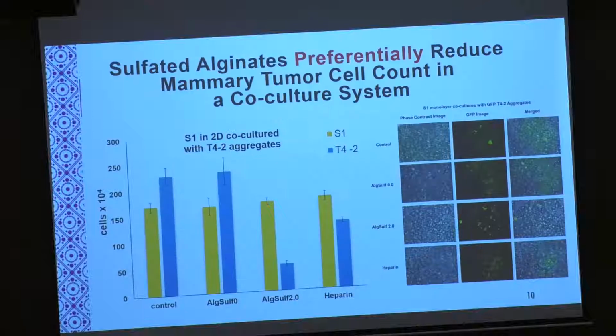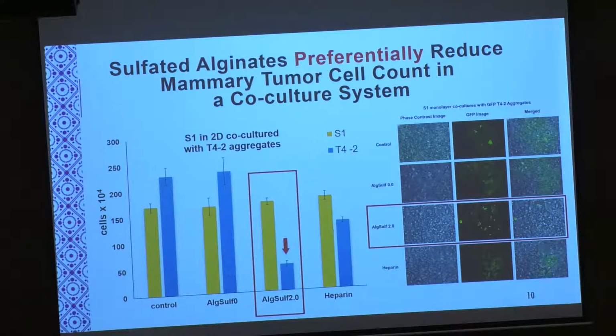And finally, we're saying all the time that these alginates are preferentially reducing the proliferation of the cancer cells and not the normal cells. So a co-culture system was a perfect approach for us. We cultured S1 cells, and we added on them T4 cells that are GFP labeled. GFP means green fluorescent protein, so they basically fluoresce under a fluorescent microscope. And we counted the number of cells post-treatment. The number of S1 cells, the yellow bars, was consistent throughout. But the number of viable cells in the T4 decreased dramatically, mainly with the alginate sulfate 2.0.